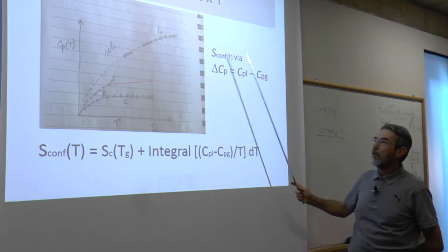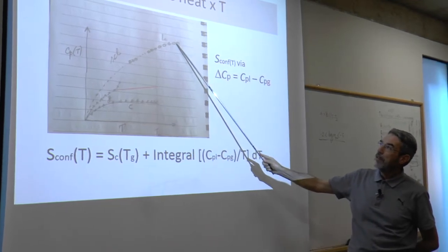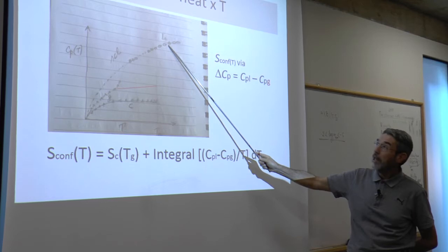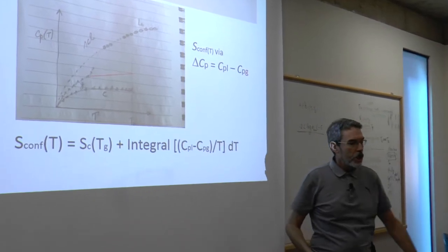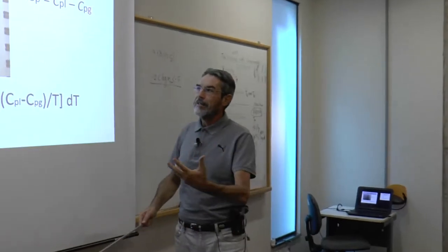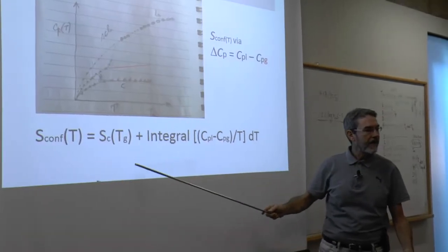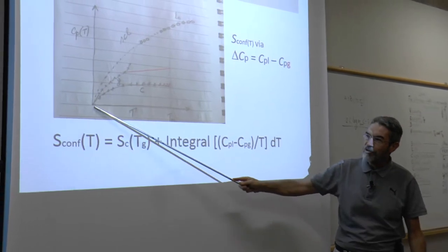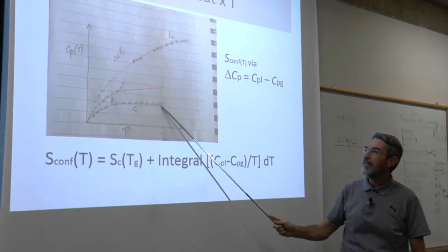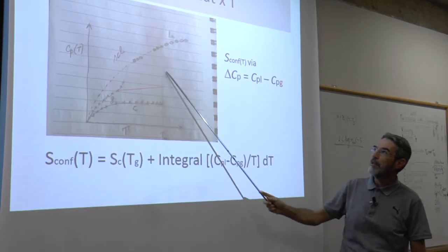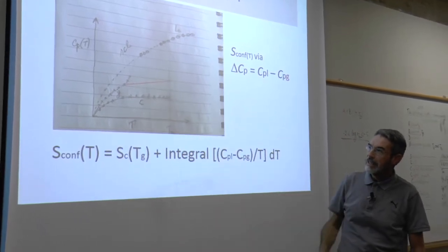Now, you can also go above the melting point and measure the specific heat of the true liquid, and also a little bit here of the undercooled liquid before it crystallizes. Okay, in the end, experimental data points for the crystal, no problem. If you have a very good calorimeter, you can go from almost zero, this is 0 Kelvin, up to the melting point, then it melts. This is melting, jumping Cp. Then you can measure the liquid and the supercooled liquid in the glass, and you have this curve here.